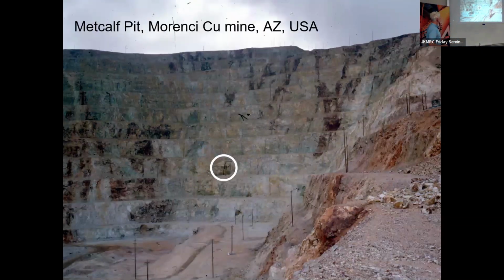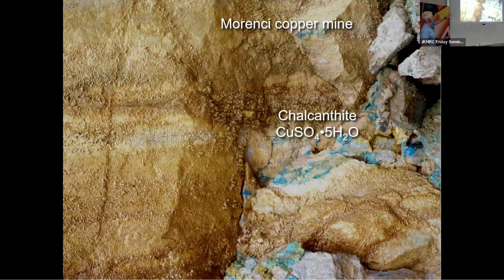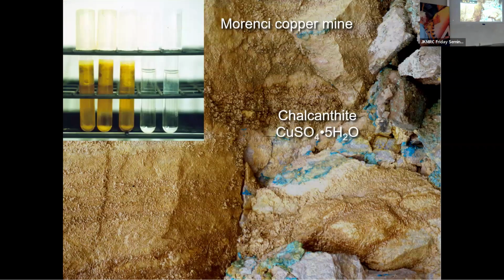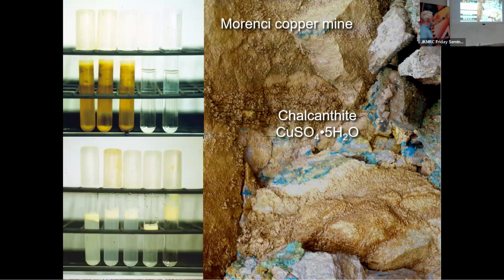We can go to the Metcalf pit in Morenci, where there's fractures, there's bacteria, and they're mining 400,000 kilos of copper per day with bioleaching. And so again, another example of bioleaching being an easy thing. We can zoom into that fracture, and you've got chalcanthite right at the surface, and whenever it rains, that copper will dissolve and goes into their solvent extraction electrowinning process. And so an easy example of bioleaching there. They're even discussing the idea of stopping conventional mining and just pumping fluids around, like copper, and they'll mine that way. And we've got our iron and sulfur oxidizing bacteria thriving in this kind of environment.